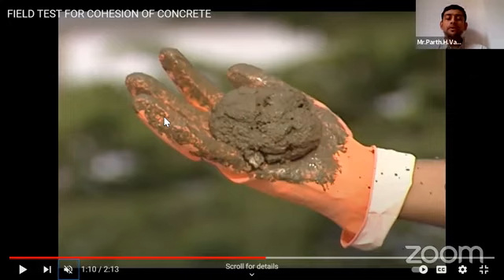This test is particularly for cohesion, which means that checking only one thing is not enough. The other height, up to 1.5 to 2 feet, is also important, because the ball can stay as it is, as shown in the first case, even when the concrete is not cohesive and has less water content than required. So this test is for that. The first shows whether the water is higher, and the second shows whether the water is lower. After both tests, we can say that the water and aggregate proportions are okay.